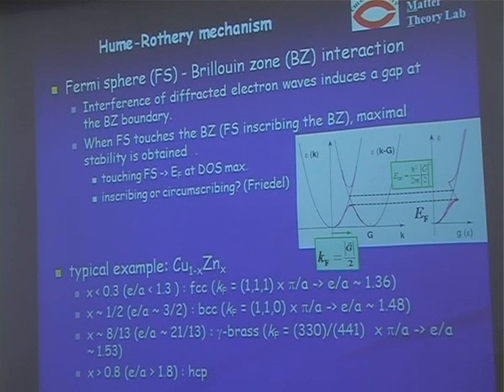Such a stability mechanism, or gain of the band energy, is realized in typical alloys, that is, copper and zinc alloys. And in this system, depending on the zinc concentration, we can change the E over A because copper is monovalent and zinc is divalent. And also depending on the concentration of zinc, we have several different crystalline structures. And these crystalline structures are consistent with the assumption that the Fermi sphere touches the Brillouin zone for these crystalline lattices. So that's why copper-zinc is a typical example of the Hume-Rothery mechanism, typical Hume-Rothery alloys.